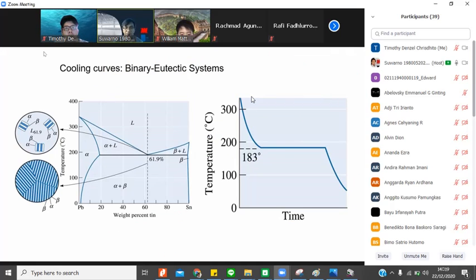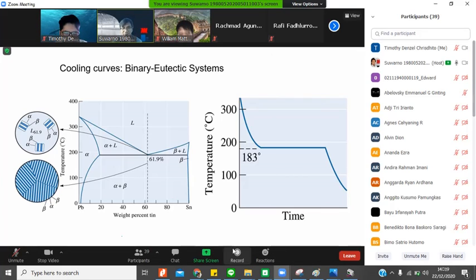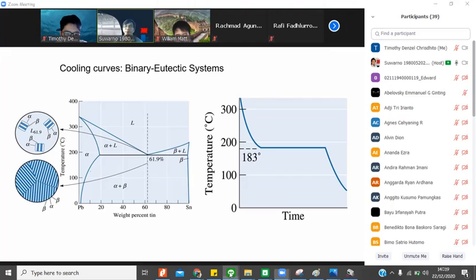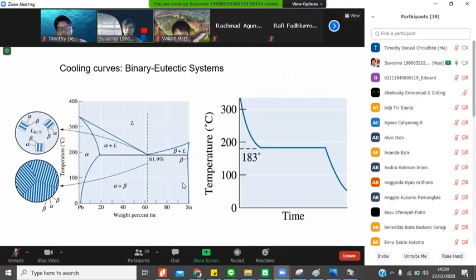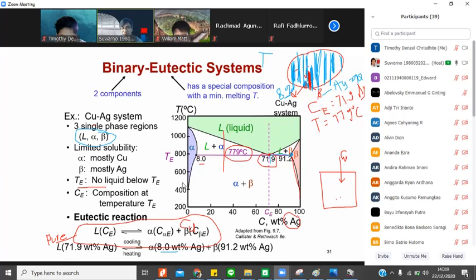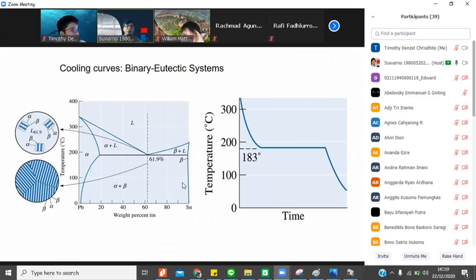This example is basically for the PB-SN system, and for PB and SN system, this eutectic occur at different temperature and different composition. This for Copper-silver, it is occur at 779 degrees Celsius and 71.9% of silver. But for PB and SN, it is occur at 61.9% Sn and at 183 degree. So this is 180 degree. 183. Okay, this line. This is 183.